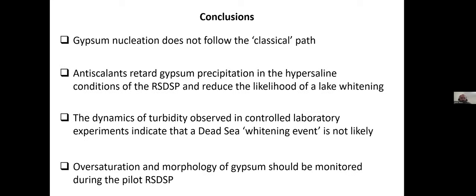And some conclusions of the talk overall: gypsum nucleation does not follow the classical path. Scale inhibitors retard gypsum under the conditions of the Red Sea-Dead Sea project, and they reduce the likelihood of a whitening event. The dynamics of turbidity we saw also suggest that there would not be a whitening event. However, again, we should be cautious because small-scale laboratory experiments are not the natural system. And the oversaturation and morphology of gypsum is what we want to monitor if there's a pilot stage, since from what we said, those are the factors that will determine whether a whitening event will develop or not.